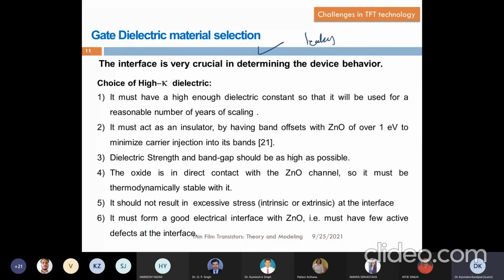You want the current to flow from source to drain, while you don't want current flowing from gate to substrate. There should not be any current, right? If you want to avoid the leakage current, and leakage usually happens when you apply a higher voltage at the gate, then there could be the possibility of FN tunneling or different kinds of tunneling. So leakage may happen. What you want to assure is that whatever gate dielectric you choose gives you a good band offset with the ZnO, at least greater than 1 electron volt, to minimize the carrier injection. So all these properties together decide the choice of dielectric.